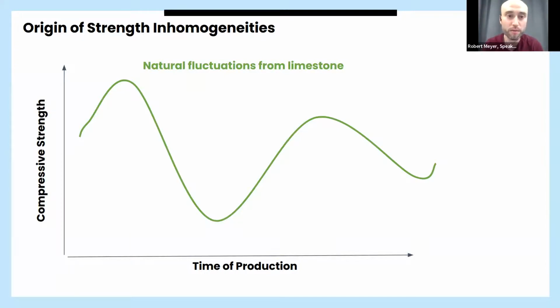Because if you look into a limestone quarry, every cubic meter looks very, very different. You can see it by the colorful stones in a limestone quarry, there's lots of variation in nature. So this is what you can see here. Maybe last Tuesday I got very, very fine limestone, which produced cement that got very strong. But a week later, I'm unlucky and my limestone is not that good in its chemical and mineralogical composition, and I get some cement that doesn't get that strong. So this is how these fluctuations in the cement strength happen over time of production.